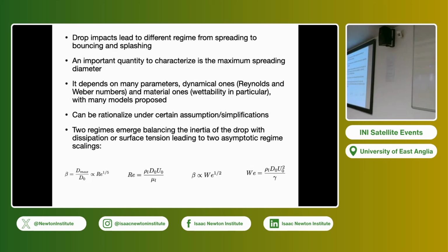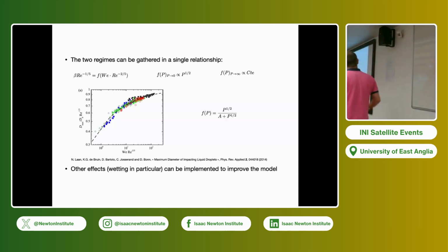As you spread, you create new surfaces, so you have to give more surface energy. If you don't consider wettability so far, the spreading ratio beta, the maximum radius divided by the initial radius, should go like Weber to the 1/2. There has been a lot of experimental work on that, and what we have used is that you can rescale these two laws and put them in a single law. If you divide this radius ratio by Reynolds to the 1/5, and you plot that as a function of Weber times Reynolds to the minus 2/5, you can show that all the data from the literature collapse on a single curve, which was a way to prove that this law was probably the correct one compared to other laws.